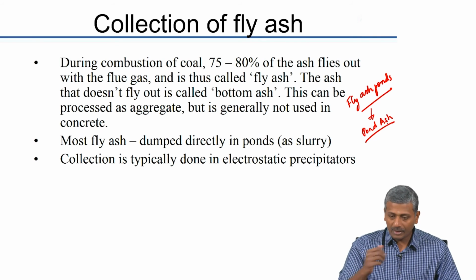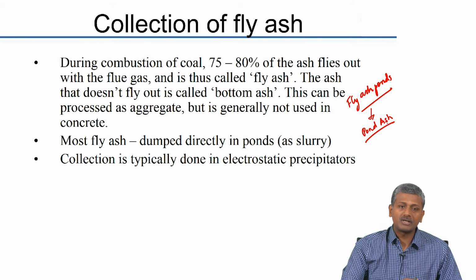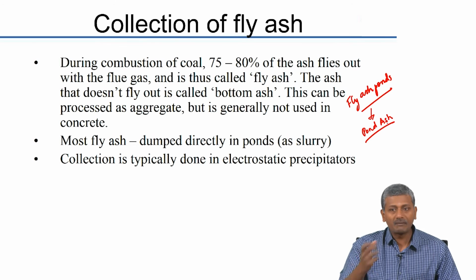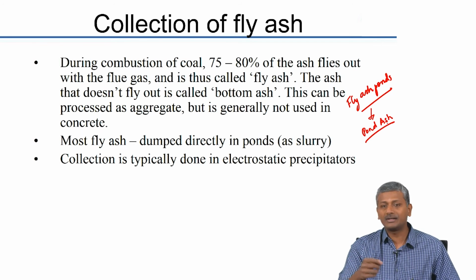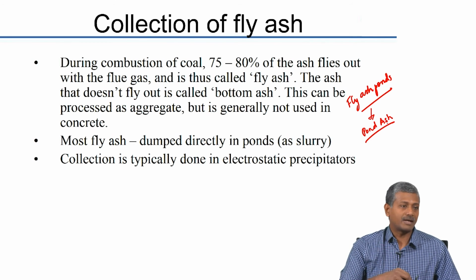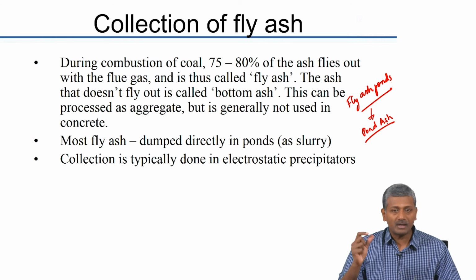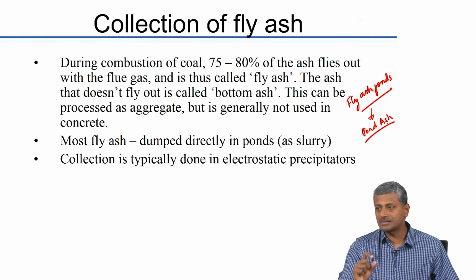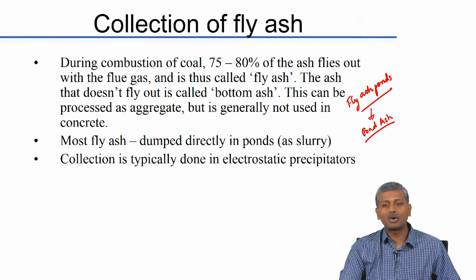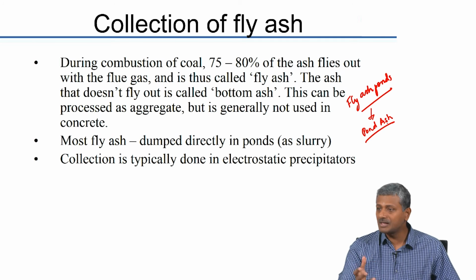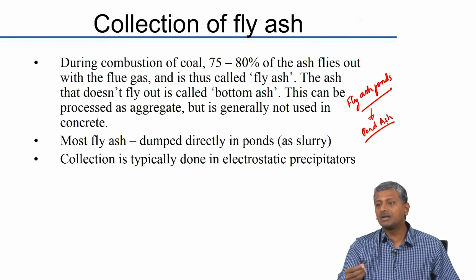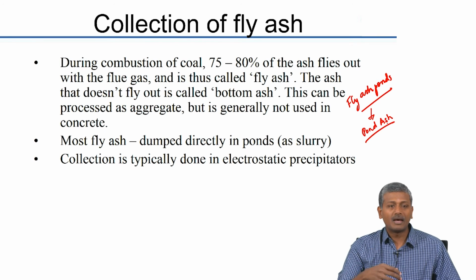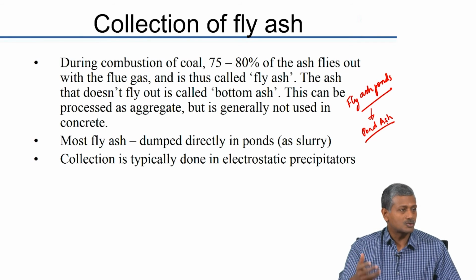Okay. In our lab, Professor Ramurthy's students have actually done some work on retrieval of pond ash and conversion of that into a sintered fly ash aggregate. So, they actually pelletize it and sinter it into aggregate size, and they have been quite successful at obtaining pond ash aggregate with this. So, that is a very interesting way of looking at things. Only problem is when you turn it into an aggregate, you need to give a lot of energy input into the system, and that may sometimes act against your intentions of actually using this fly ash.